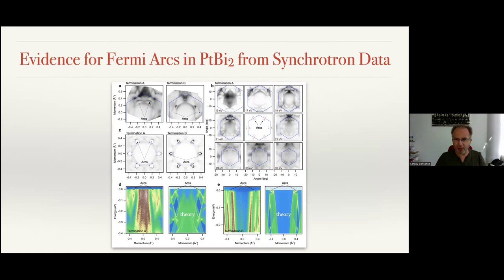And here you start to see arcs, these small points here. It was tempting to say that this is arc, but this is not. This is this feature from the calculation. So the arcs are these small points here. Difficult to resolve at the synchrotron, but nevertheless, in the vertical slice of the onion, you can clearly see these two. This is horizontal slice, and this is vertical slice. Again, as the theory predicts, these features are there.